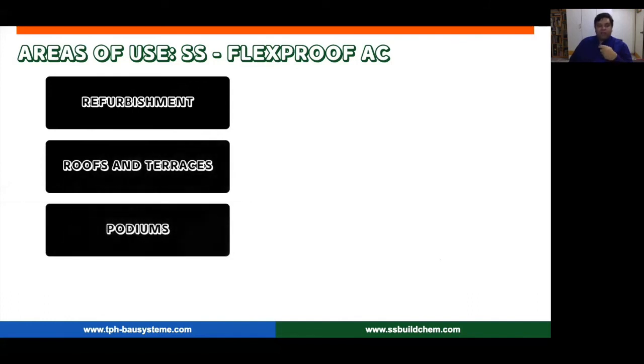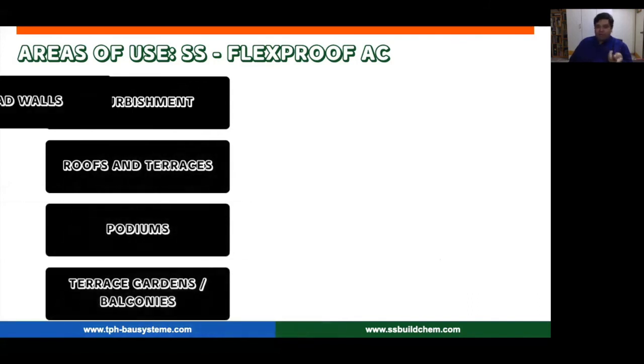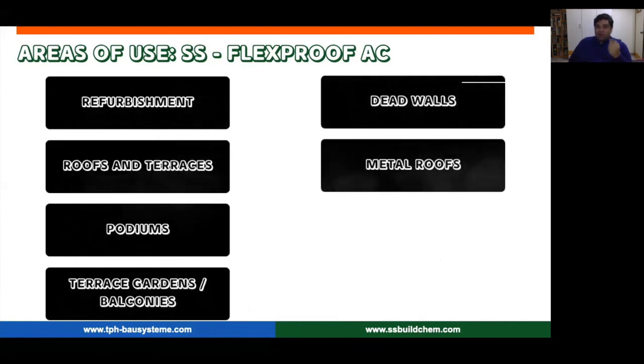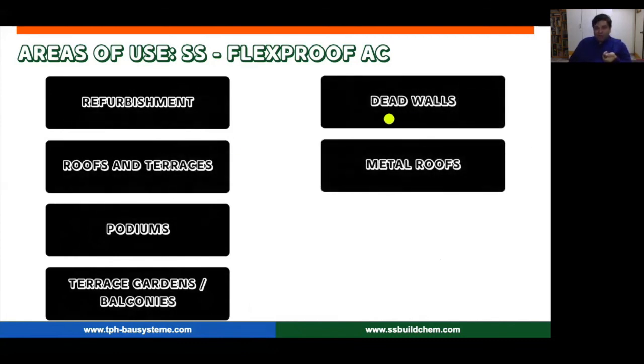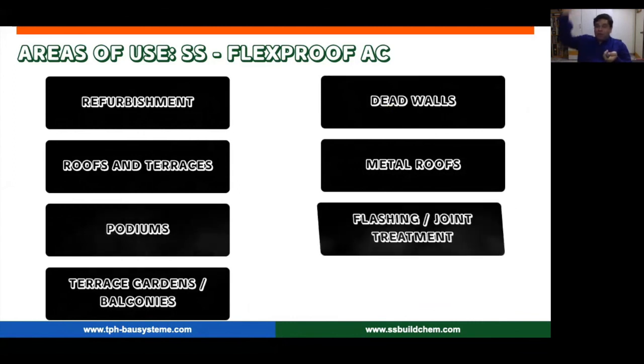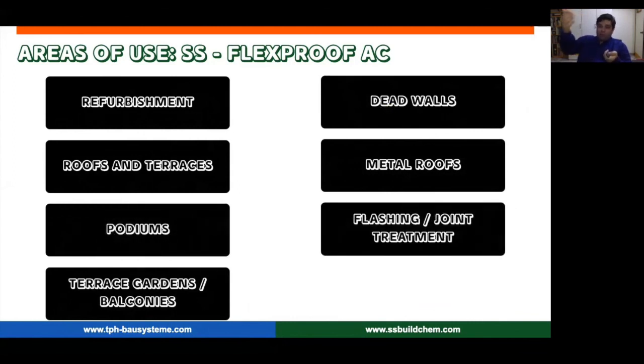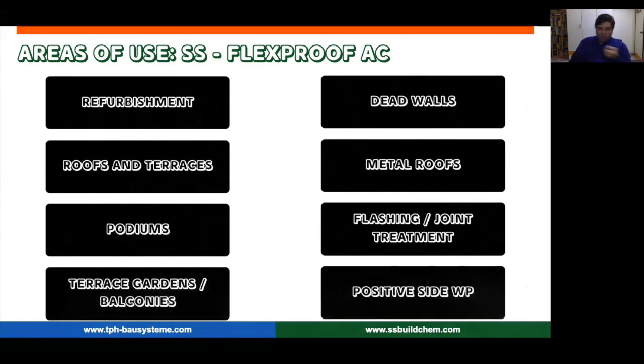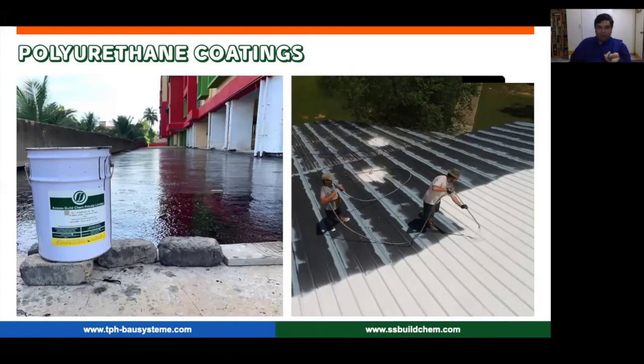We use it for roofs and terraces, in places like podiums, terrace gardens, balconies. One of the main good applications you can use it for is dead walls. So all your building external walls, which are prone to water coming in frequently during the monsoon, you can simply use this coating. You can get this in different colors. So it makes your life very easy and at the same time also protects your building envelope very well. You can use this for metal roofs, as well as for different kinds of flashing or joint treatment. It's better to use this more in positive side waterproofing.